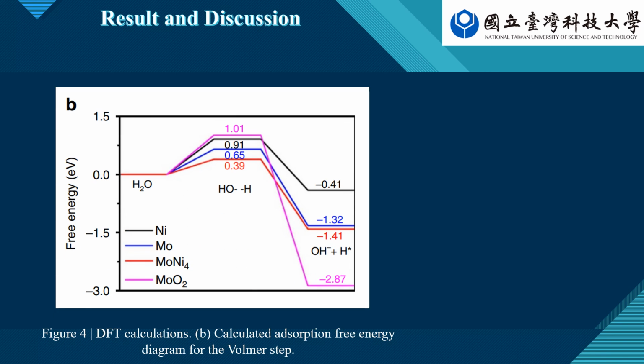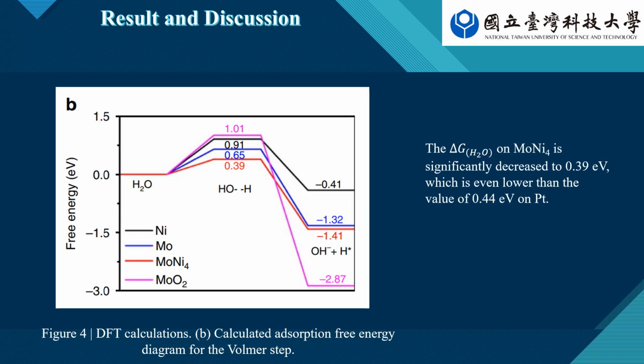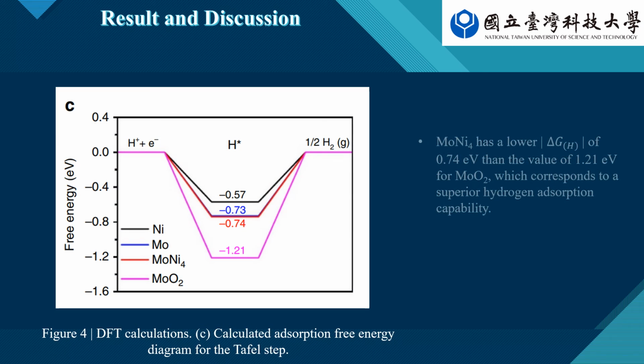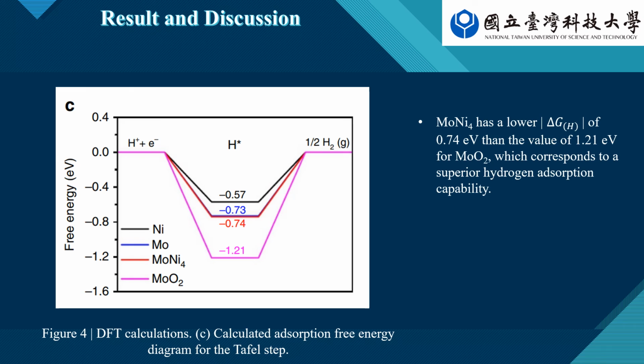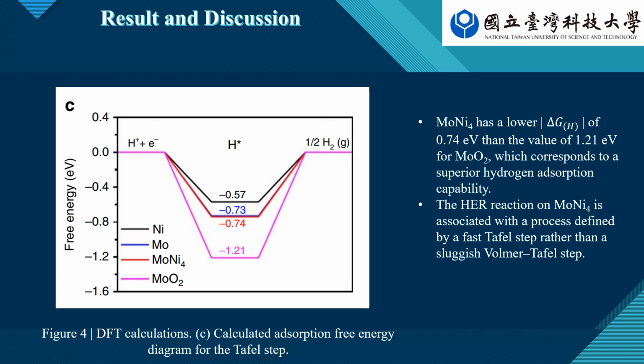Figure 4b is the calculated adsorption free energy diagram for the Volmer step. As shown in this diagram, the Gibbs free energy towards water on MoNi4 is significantly decreased to 0.39 electron volts, which is even lower than the value of 0.44 electron volts on Pt. From figure 4c, in addition, MoNi4 has a lower hydrogen free energy of 0.74 electron volts than the value of 1.21 electron volts for molybdenum dioxide, which corresponds to a superior hydrogen adsorption capability. Thereby, the HER on MoNi4 is associated with a process defined by a fast Tafel step rather than a sluggish Volmer step.